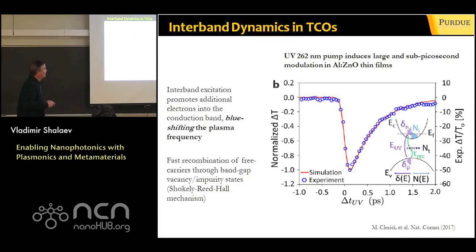And as a result, you have this transmittance which drops. And look, the relative change of transmittance is truly dramatic. It's almost 50%. It's an exception. It's very unusual for a nonlinear response to be that large. It's a nonlinear response, and we're talking about a change in transmittance of like 50%. In liquid crystals, you sometimes have that large a response, but they are typically very slow.